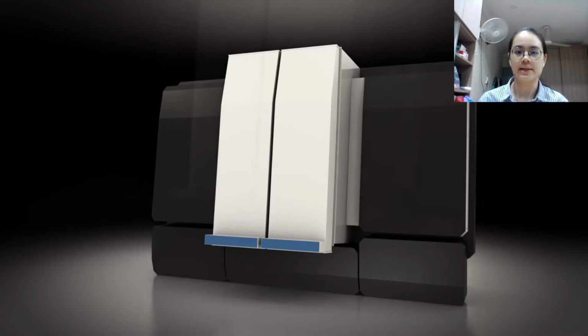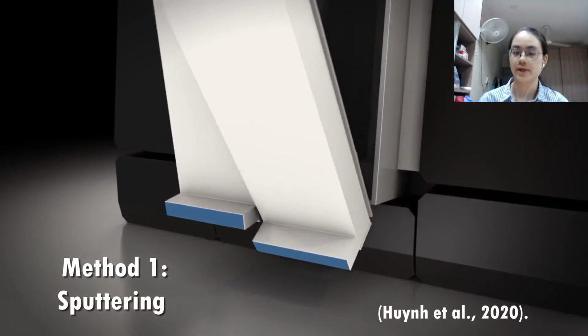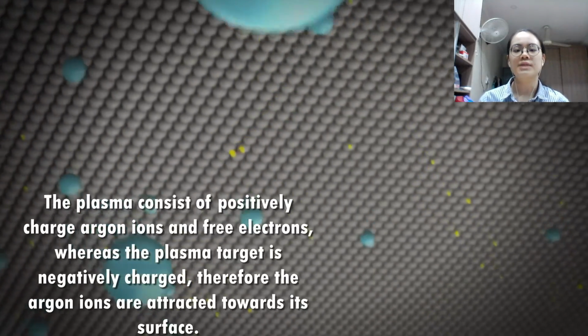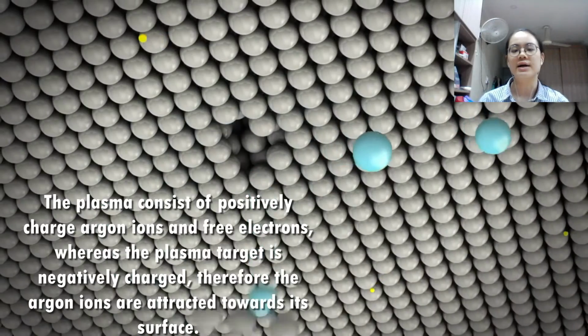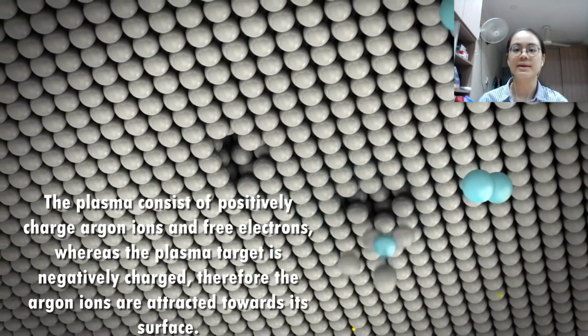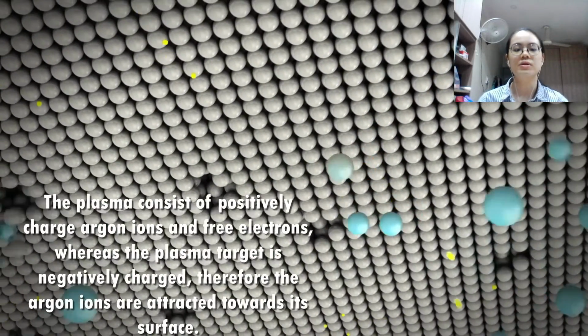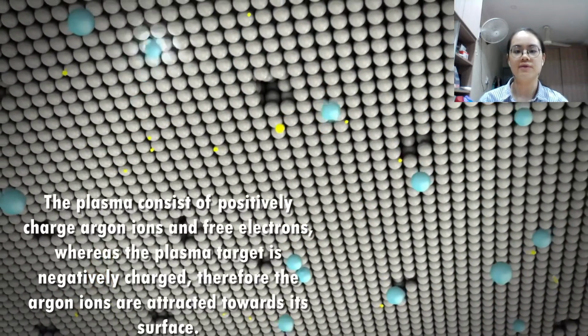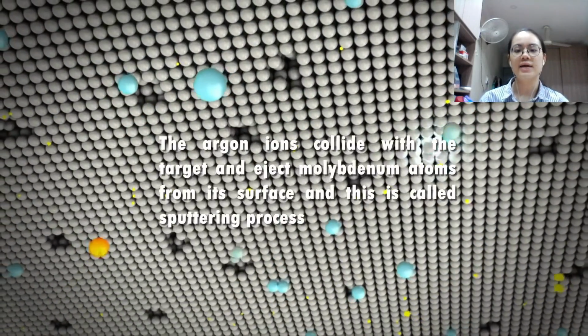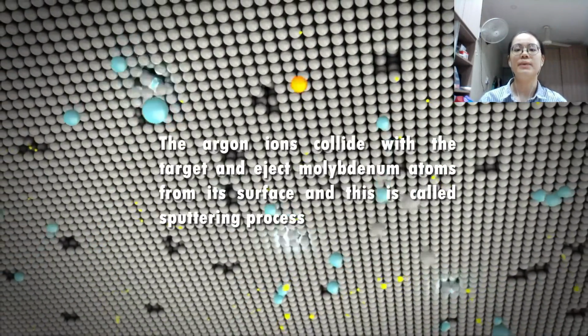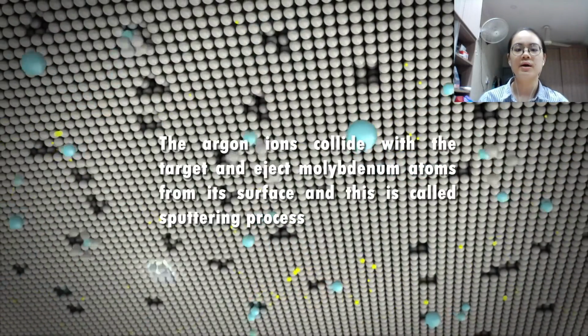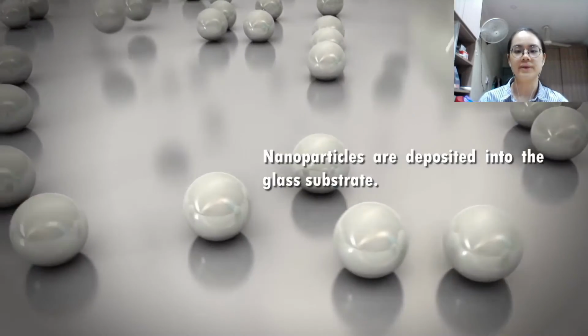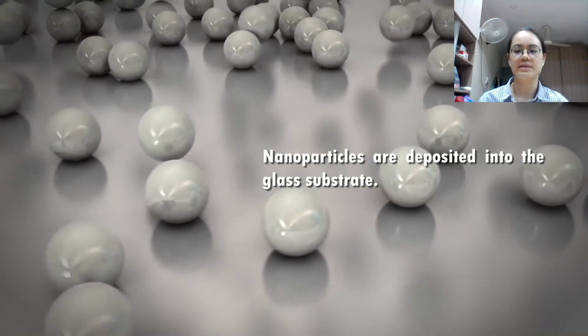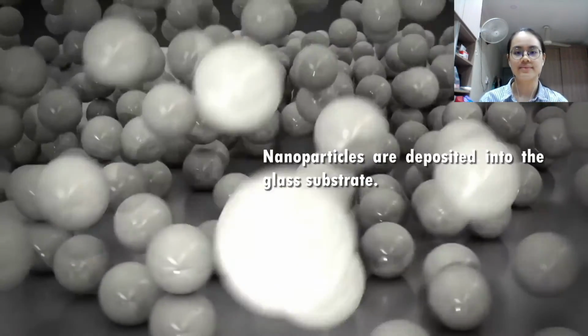There are 6 methods, and the first method is sputtering. The plasma consists of positively charged argon ions and free electrons, whereas the plasma target is negatively charged. The argon ions are attracted towards its surface, and the argon ions collide with the target and eject the molybdenum atoms from its surface, and this is called sputtering. And the nanoparticles are deposited onto the glass substrate.